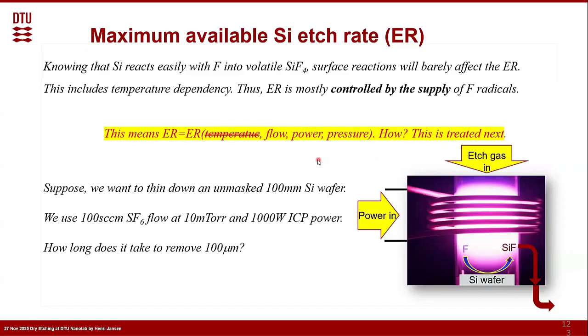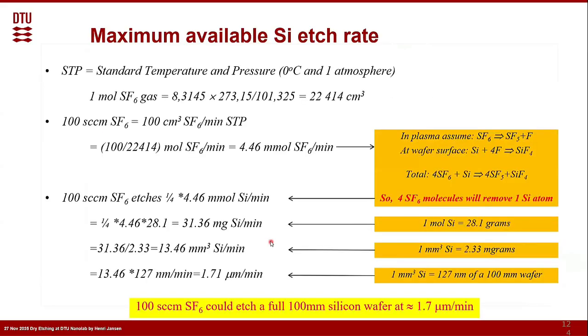And we first ask, suppose that we want to thin down an unmasked 100 millimeter silicon wafer. And we use, for instance, 100 SCCM of SF6 flow at 10 millitorr and 1000 watts of ICP power. And I would like to know, how long does it take before I will etch 100 micrometer of this 100 millimeter wafer? How to go around that?